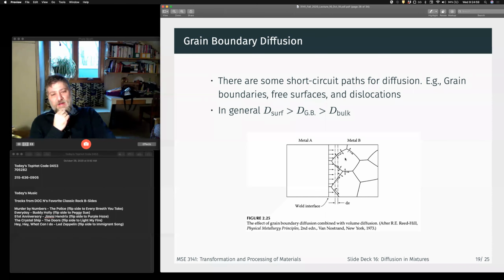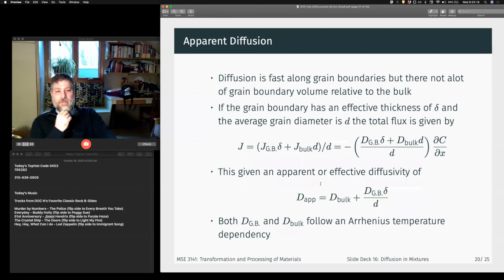And so atoms, in this case A, if we look very near the grain boundary, A will penetrate much farther along the grain boundary than it will in the bulk, right? But again, we have to consider the relative amount of grain boundary volume relative to the bulk. So if we say our grain boundary has some kind of effective thickness, and we have a grain boundary diameter, we can calculate the effective volume that transport can happen through along the grain boundary relative to the bulk. And we can calculate an apparent diffusivity that's a combination of bulk diffusion and grain boundary diffusion, right?